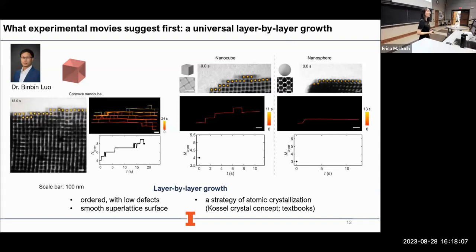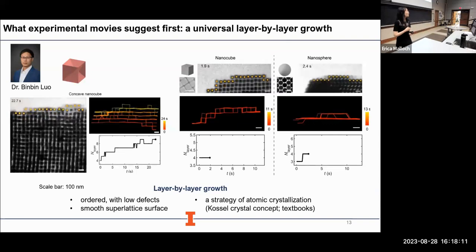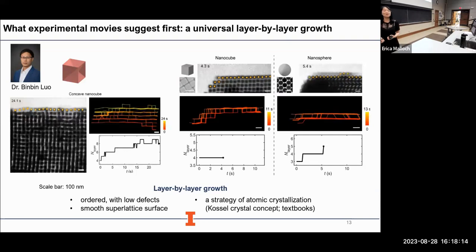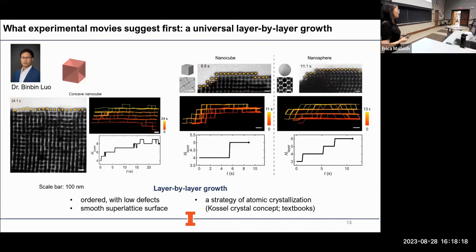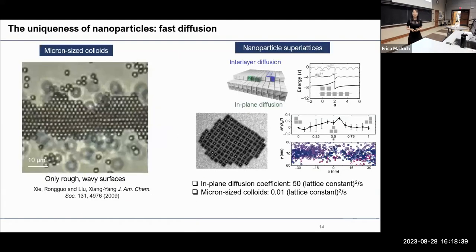This is the so-called layer-by-layer growth. If you look at the other two examples, although the shapes of the particles, the interaction potentials, and the lattice symmetries are different, they also follow the same layer-by-layer growth. Layer-by-layer growth is also a mechanism that atomic building blocks frequently adopt. That's why you can easily have atomically flat thin films for the semiconductor industry. So does it mean layer-by-layer growth is a universal growth habit for crystals? That's not really the case.